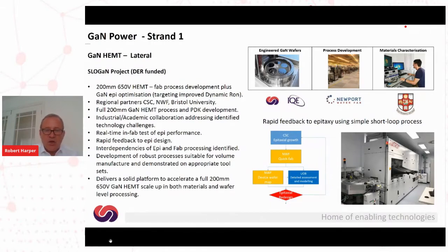The project name SLOGaN, the first three letters stand for short loop optimization of GaN. And we are making some really interesting finds by having this short loop process, which allows us then to make iterative improvements to the epi design. And we've actually modified the epi structure quite significantly through this project. And we've certainly ended up with a more robust epi product as a result of that.